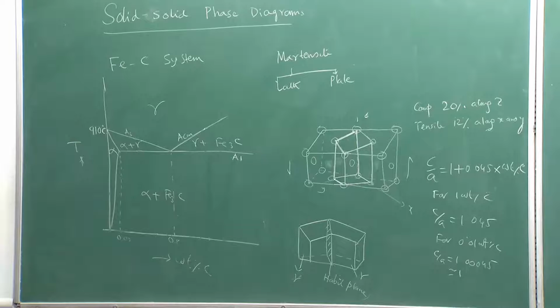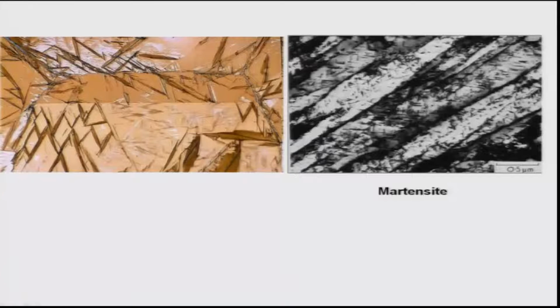Like this one I showed you here, you see these are the plates in this picture. This is an optical micrograph which I am showing you here. You can see these are the prior gamma grains, 1, 2, 3, 4, 5 gamma grains. You can even see the boundaries, and the martensites have formed like a tree branch or leaves of a tree. They are actually called laths of martensite. On the other hand, here you see they are plates of martensite. So, these are the two typical morphologies of martensite. In the next class we will discuss more on martensite, and I will tell you the basic theories behind it, because martensite transformation is very important for steel metallurgy.